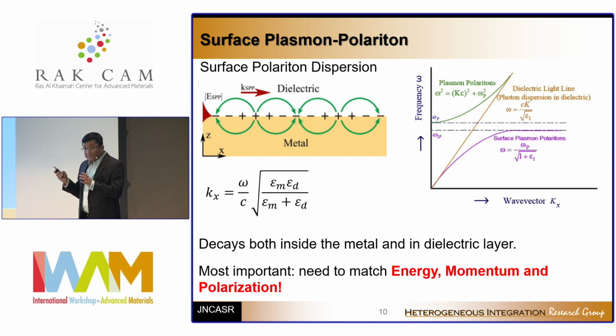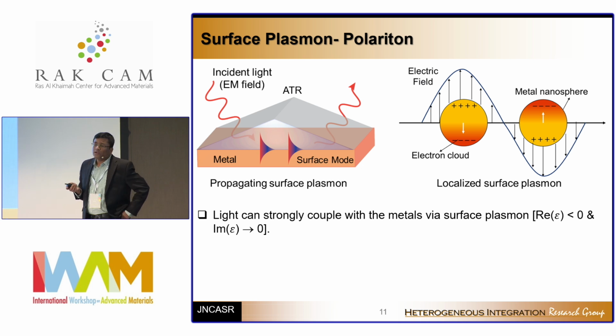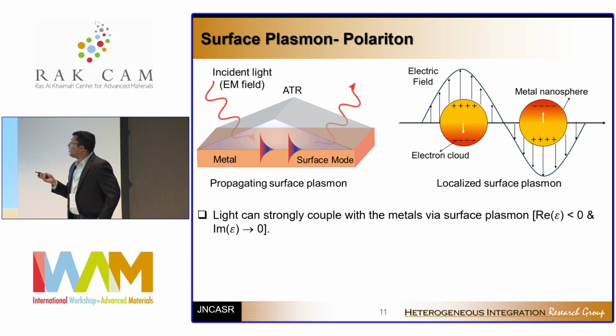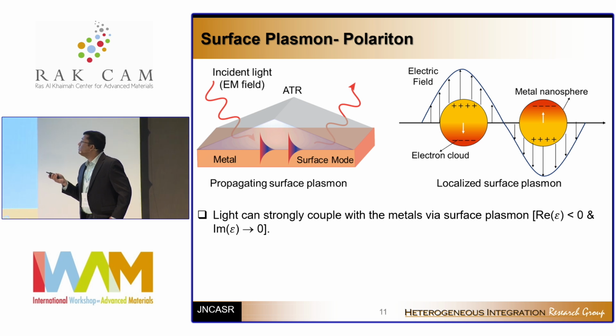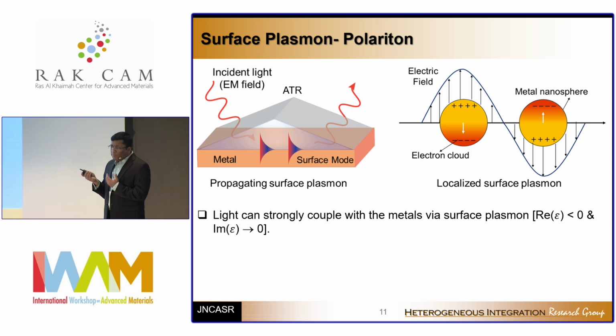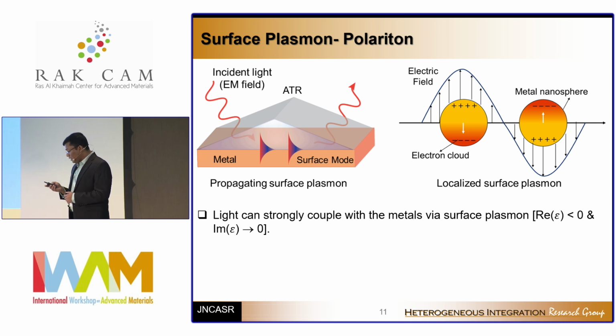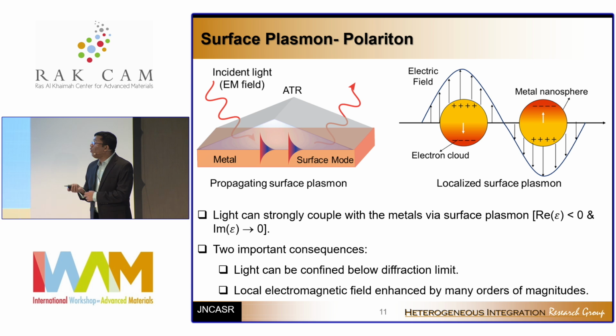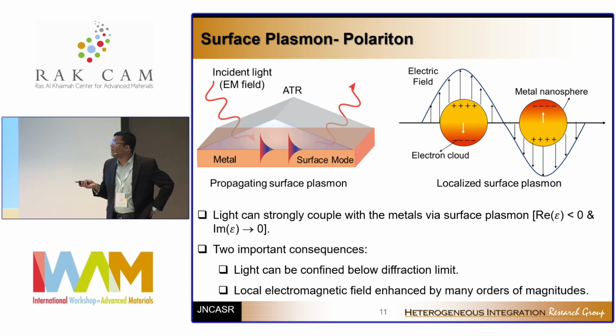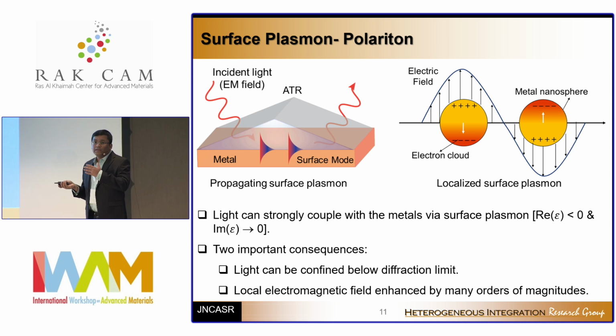So one of the things that you always have to worry about, or always have to make sure of if you try to excite polaritons, any type of polaritons, is that you have to match the energy, the momentum, and the polarization of light with that particular excitation. And that is why traditionally, or at least a simple way of exciting a surface polariton is just by putting a high dielectric constant material, which is diamond in most of the cases, on the surface of a metal to excite the surface polariton. Some people also use nanoparticles to excite the surface polariton resonances, and they basically offer a way of confining light below the diffraction limit, and at the same time, you can increase the electric field by many orders of magnitude with this principle.